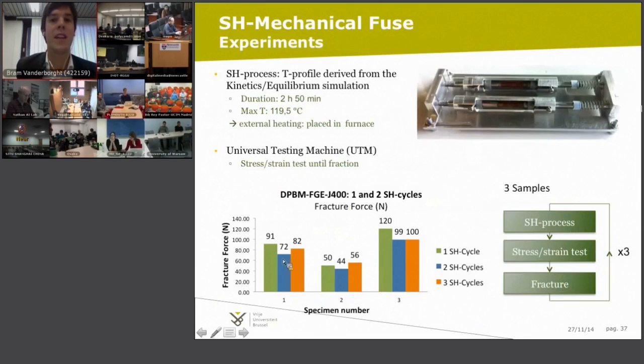So you see that we have three samples, and you see that the fracture force differs for the three. The reason is that we produce it manually, and it's quite small, because to produce such material is not so straightforward. But you see that there is no weakening of the element, and that it almost maintains the same fracture force, which is an advantage, because that means that it can maintain the strength even after self-healing.